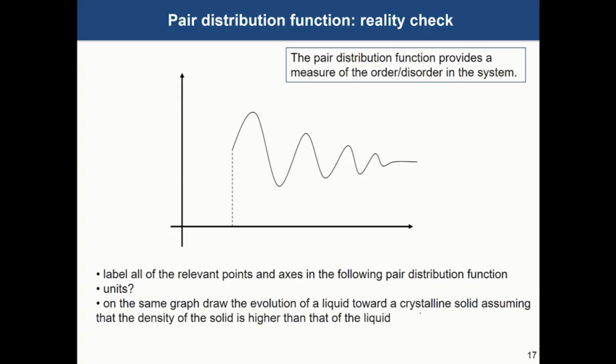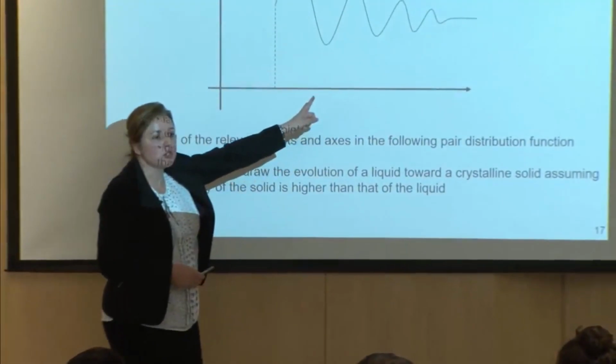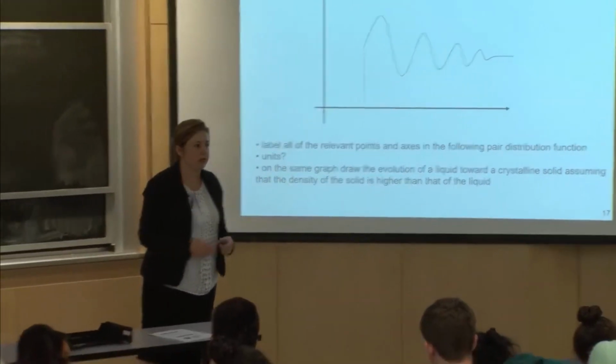an amorphous material, and we know it's an amorphous material because it has these wiggles. It's not defined, it's not crystalline, it's not gas, so it's kind of an amorphous material that has relatively long range order. So there are at least 1, 2, 3, 4 nearest neighbors. So this is relatively long ordering in a non-crystalline material.